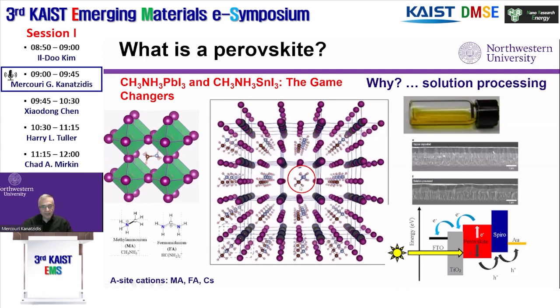And then only 3 cations fit in those cages: methylammonium, formamidinium, and cesium. If the cation is bigger, any bigger than that, then it doesn't fit in the cage and destabilizes the structure. It doesn't form. If it's too small for the cage, then it still destabilizes the structure. So it's only these 3 cations that readily go in there.